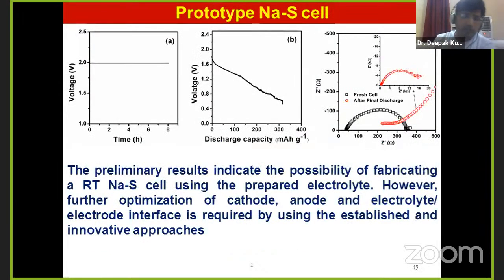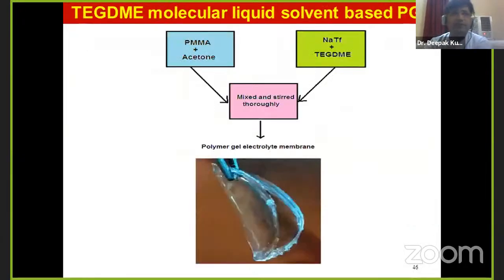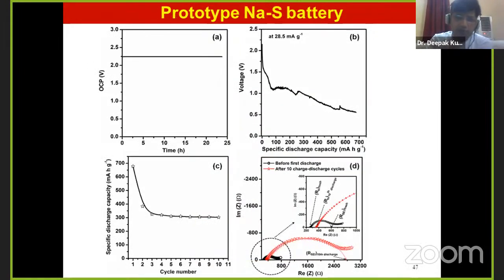So then we have checked the OCV of the battery assembled using the electrolyte system. The OCV was 2 volts, and the discharge capacity was 300 milliampere hour per gram. What we observe is, after the discharge, the impedance is increasing, and that's why the capacity is fading. So for addressing this issue, we have fabricated one more system in which TEGDME has been incorporated, and PMMA has been utilized. For such systems, we are getting a somewhat higher OCV, approximately 2.25 volts, and a discharge capacity of almost 700 milliampere hour per gram, which subsequently decreases a bit. However, after 10 cycles, the discharge capacity was 300 milliampere hour per gram.